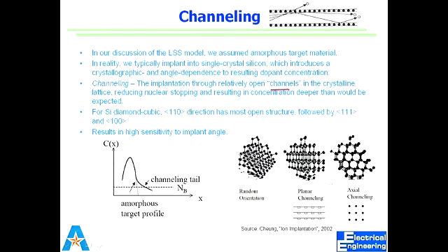It doesn't stop. It doesn't come into contact with a nucleus, and doesn't strike an electron, so it wouldn't lose energy. What we see is many more of them resulting in this tail, which is non-ideal and moves away from the Gaussian distribution. They sneak their way through. In a random orientation, there will be equal probability of collisions for every ion.